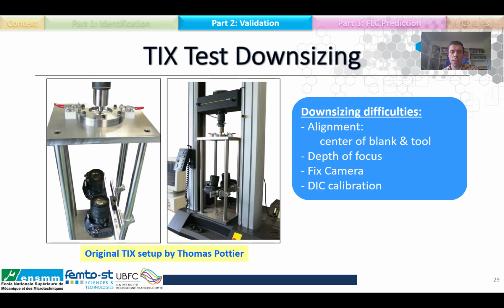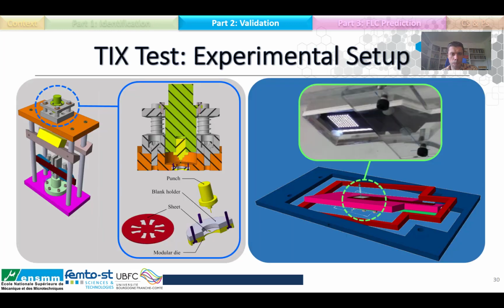So this generates different problems: a very limited depth of focus, and a requirement of having the camera completely immobile to avoid capturing blurry images. And we have exactly the same problem of focus depth and blurry image when we have to calibrate the DIC system. So after some tryouts, we have designed and manufactured the system as you can see it here. This system resolves all the difficulties we have encountered.